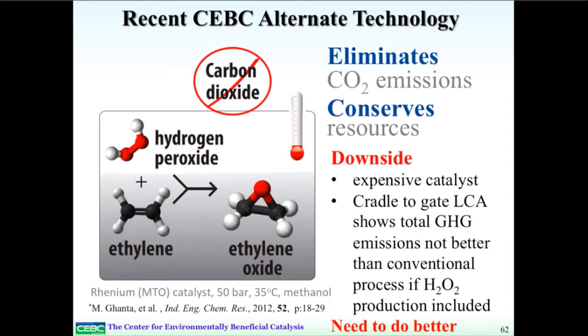of gas-expanded liquids. A gas-expanded liquid is when you have a high partial pressure of a particular gas above some organic liquid. And what you find is that in many cases that gas is highly soluble in the liquid, and so by increasing the pressure of the gas, you can expand the volume of that system. And so here we're actually using ethylene expanded methanol. So we have ethylene in the methanol phase here, at somewhat high pressures but relatively low temperatures. That's currently room temperature in Kansas. And to form the ethylene oxide. So again, this eliminates the CO2 emissions from this particular process.